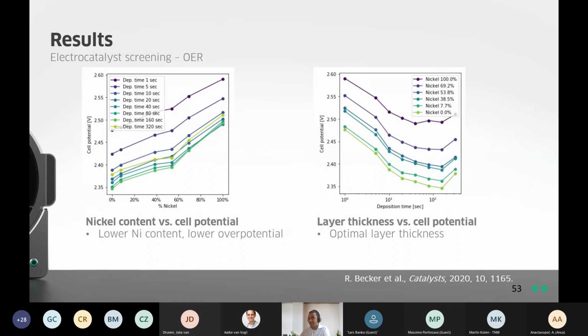So here again we have the cell. The results that came out of it. On the left here, I show you the cell potential and how this varied with different nickel content. What we see in general is that at lower nickel content, we get a lower overpotential, implying that we have a more efficient electrocatalyst for the OER reaction. On the right, I show you how the deposition time, so the layer thickness, influenced the cell potential. And what we see here is that there appears to be an optimal layer thickness, at which point we obtain the most efficient electrocatalyst for the OER reaction.